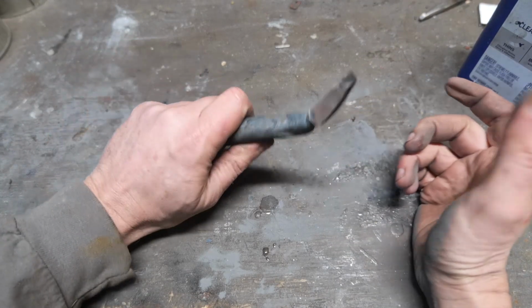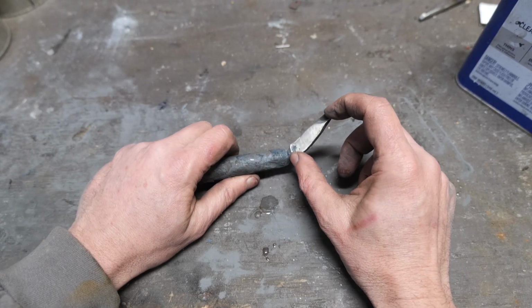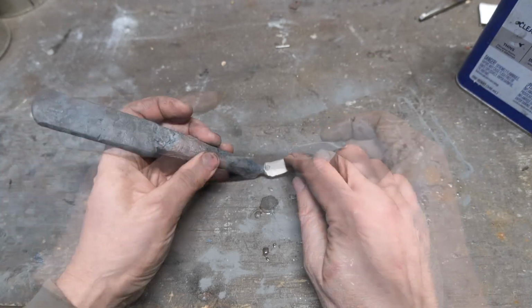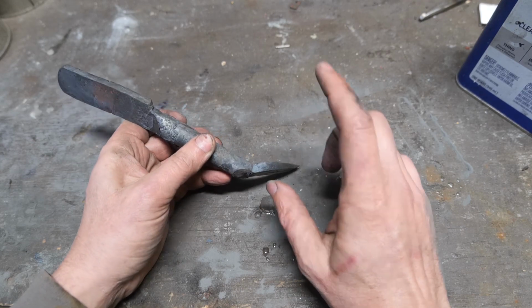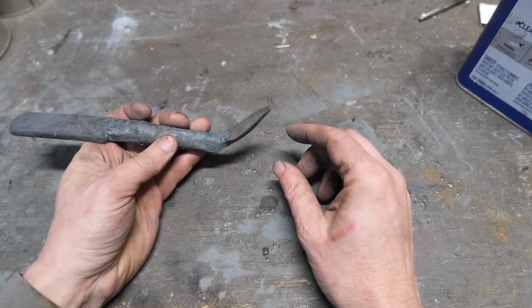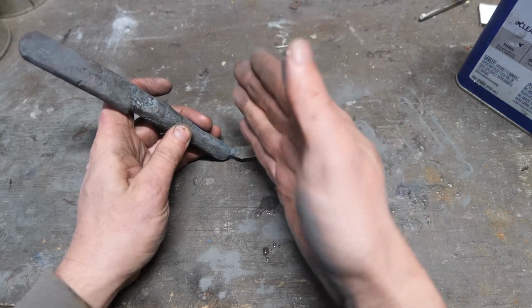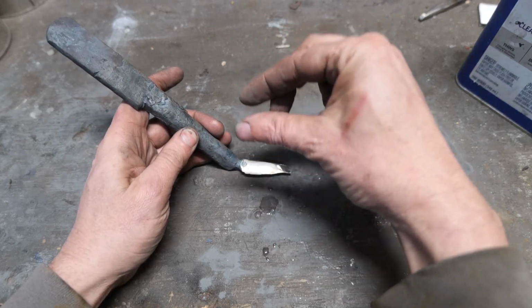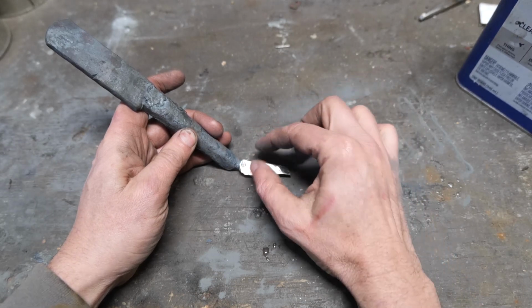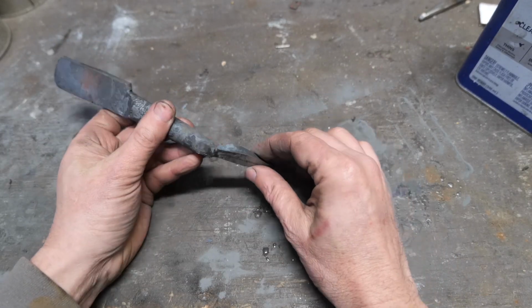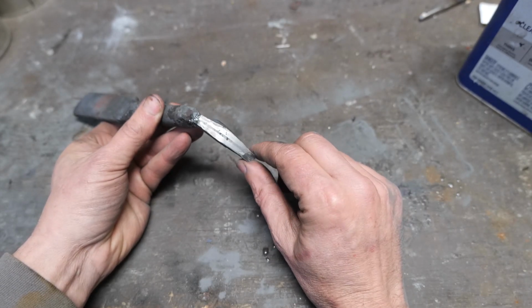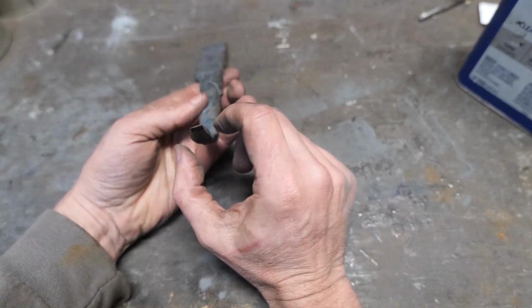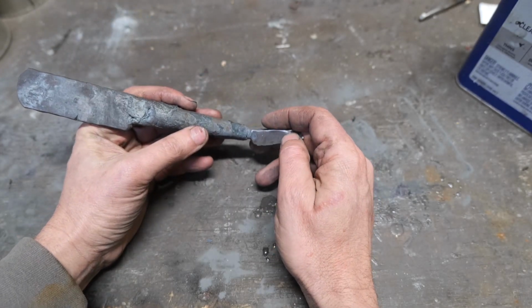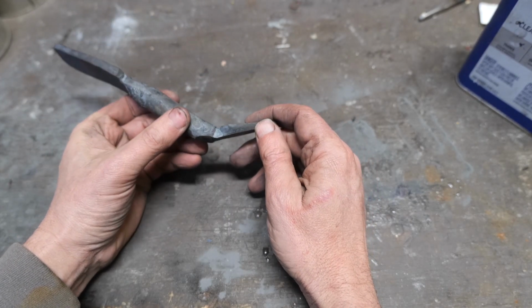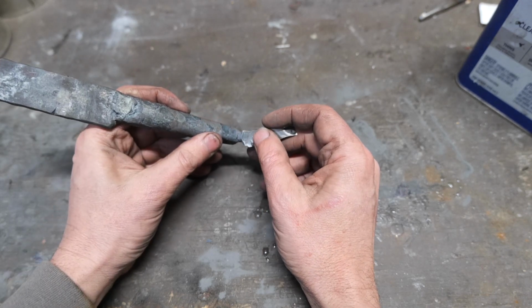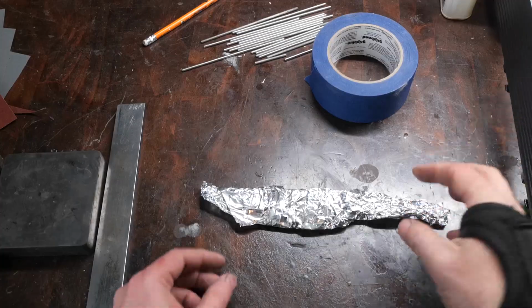Okay, so this is the handle to the second billet. This is the piece of the end of the second billet sort of folded over. And the seams, I think, are a lot tighter and the weld's a lot better. I turned this on its side on the anvil, hammered flat perpendicular to the welds, which run this way, sort of spread them apart, tried to pull them apart. Nothing popped here, very tight. There's the core running up and down the center. And here it is sort of spreading out. So you can see that that really put a strain on the forge welding and it held up really well. And that's really good for stainless sanmai. It's a little bit trickier to get solid welds.